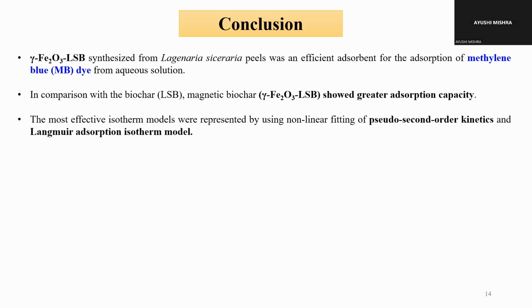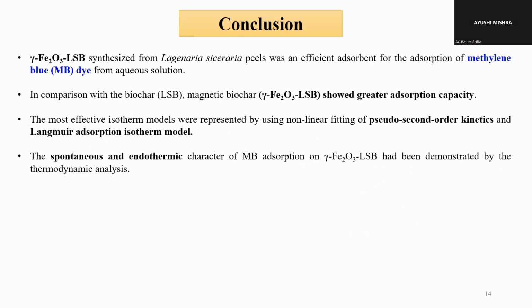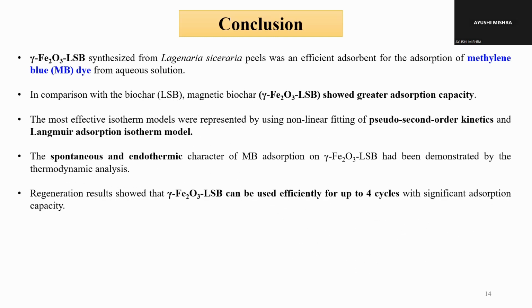The most effective model by non-linear fitting is pseudo second order kinetics and the Langmuir adsorption isotherm model, which is for monolayer adsorption. The spontaneous and endothermic character we have also obtained by thermodynamic analysis, and the regeneration results showed that it can be efficiently used up to 4 cycles with a significant adsorption capacity.